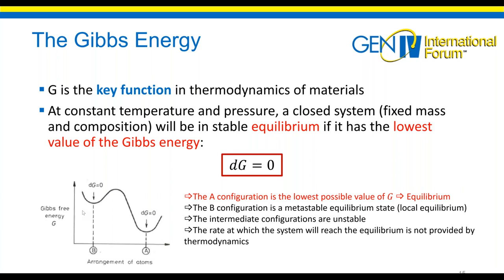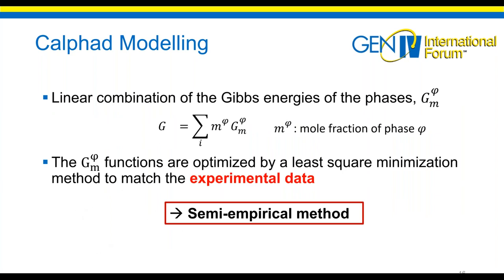And also, this G function is really useful in the thermodynamics relations, because you can derive many other quantities thanks to the G function. And so in your system, in case you have several phases, the total Gibbs energy is obtained by linear combination of the Gibbs energies of each phase. And therefore, you have the principle of the CALPHAD method, that is to optimize the G function of each phase by a least square minimization method to match the experimental data in order to be able to model your whole system. And as we are basing our modeling on the experimental data, this is a semi-empirical method.